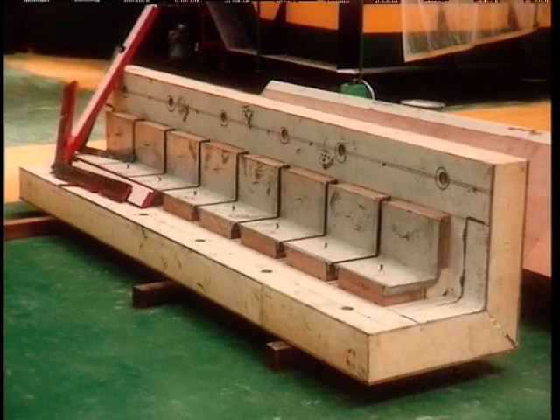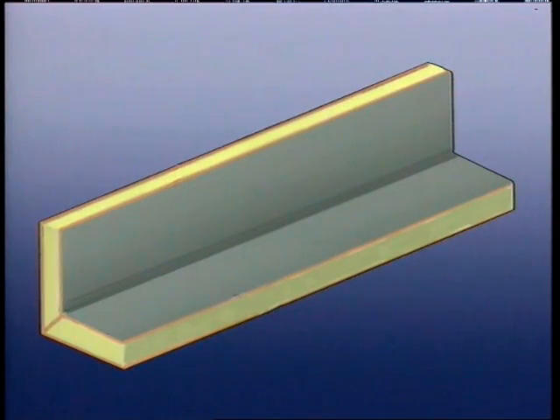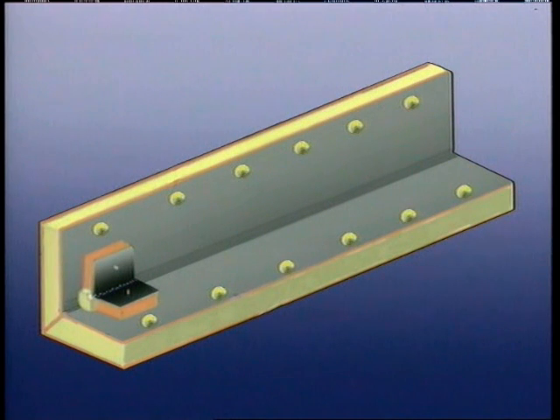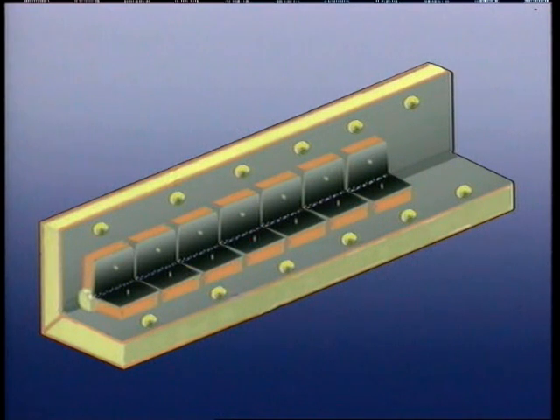The angle panels at 90 and 135 degrees are assembled by bonding in the same manner. Two sandwich panels made of reinforced foam, plywood and including a secondary barrier are held by bonding the rigid composite keys made of hardwood and heavy corners in stainless steel, 8mm thick, onto which the primary membrane will be anchored along the tank edges.